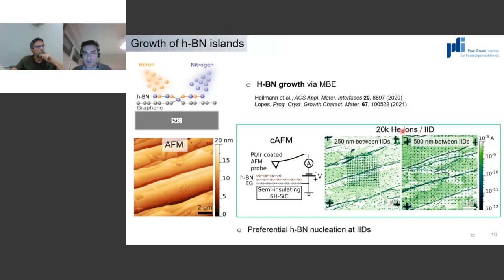And what we can see here is that for the case where we have these defects created with 20,000 helium ions per defect, we have these black dots in a pattern shape, as you would expect, because that's where we wrote our defects. This is the case where we have 250 nanometers of spacing between the defects, and this is the case where we have 500 nanometers, with a larger separation between these tiny black dots, which, according to the conductive AFM, correspond to areas where we have insulating material, much lower currents.